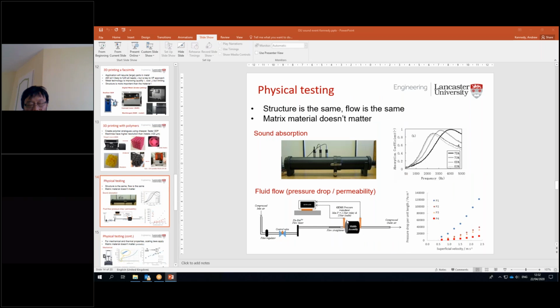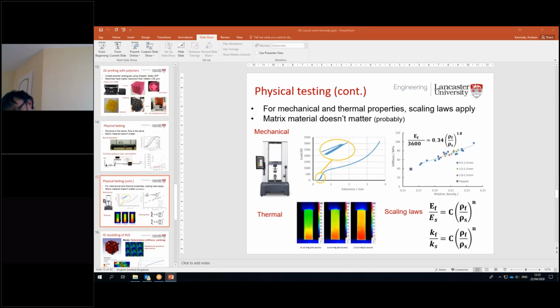So if we go on the premise that the structure is the same, flow really doesn't see the material itself, we can go about through our, obviously people are familiar with the sound absorption approach, but also fluid flow or pressure drop measurements as well. People might be slightly more concerned that when you come to mechanical and thermal properties, one would say that the material, matrix material, would be incredibly important. Some examples are shown here for mechanical testing and thermal testing based on thermal imaging.